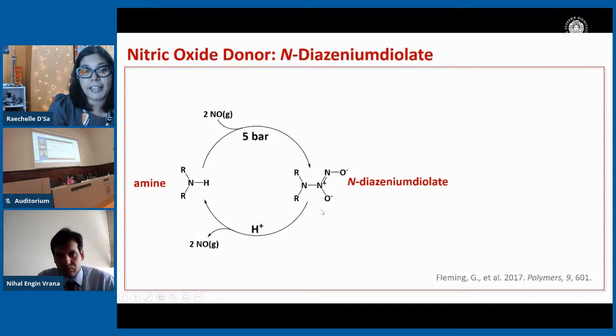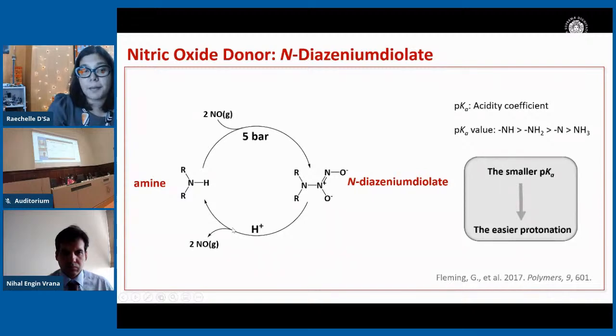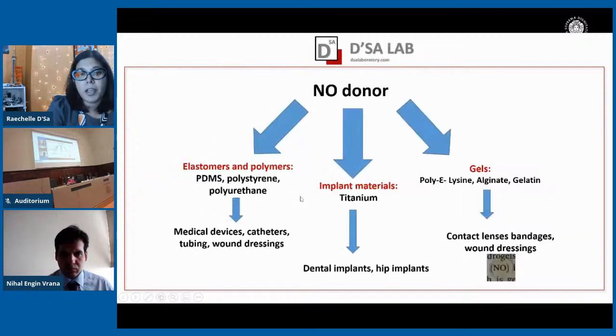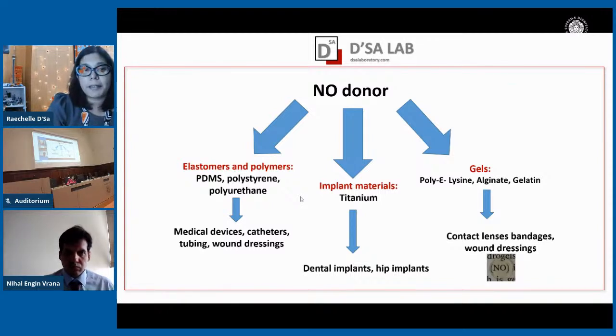This N-diazeniumdiolate can then spontaneously decompose under physiological conditions by protonating this amine to give you 2 molecules of nitric oxide. So you can control the rate of release of the nitric oxide from this donor by varying the acidity coefficient of this amino group. So essentially, the smaller the pKa, the easier it is to protonate, and the faster it will decompose at more acidic pHs. So within our lab, what we look at is lots of different applications for tethering nitric oxide onto various surfaces. And the one I'm specifically going to be talking to you about today is titanium surfaces for dental and hip implants.